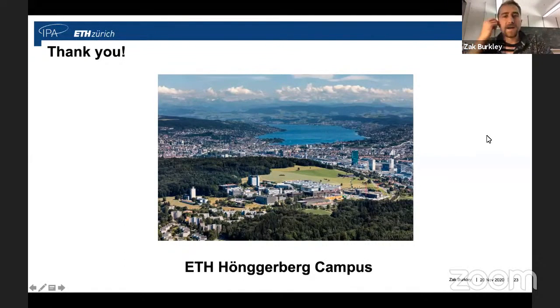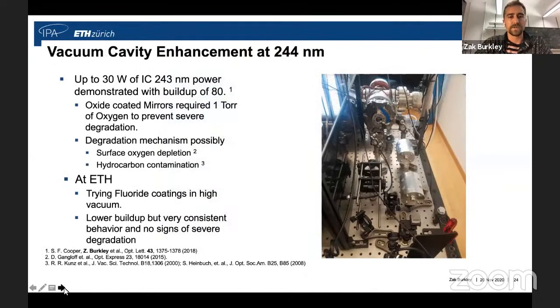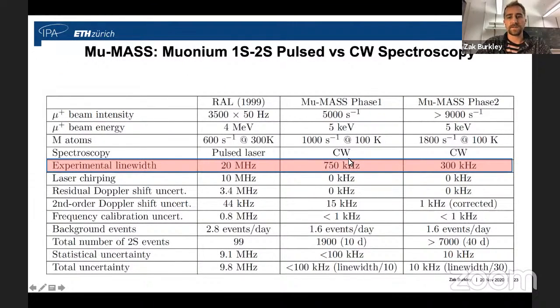Right, so we have 2 phases to this measurement, and the first phase is over the next 3 years, and we hope to get down to 100 kilohertz, 50 kilohertz uncertainty in this time. And the line width we hope to get in this first phase is a 750 kilohertz line width. And I have some plots here that maybe will help with our goals. So yeah, 750 kilohertz and less than 100 kilohertz in our phase 1.